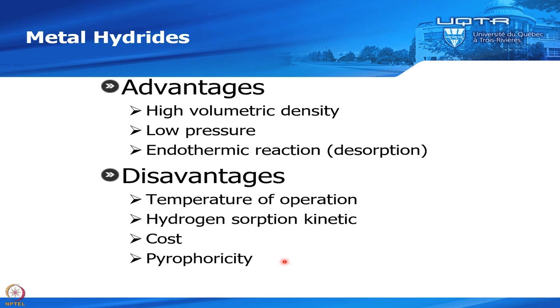And pyrophoricity, because metal hydrides, after many cycles of hydrogenation and dehydrogenation, will turn into very, very small powder. And any powder that is very, very small could be pyrophoric. And also, because metal hydrides react with hydrogen, it means that they could react with oxygen also. So you could have a problem of pyrophoricity.